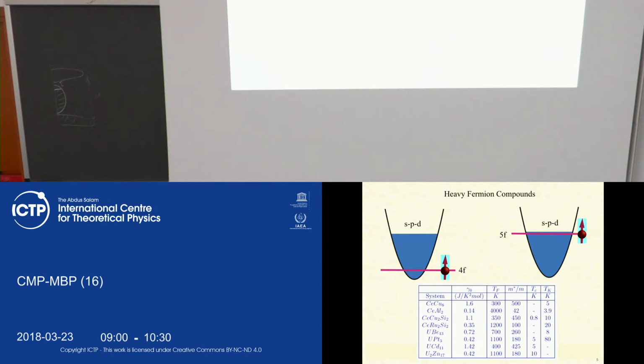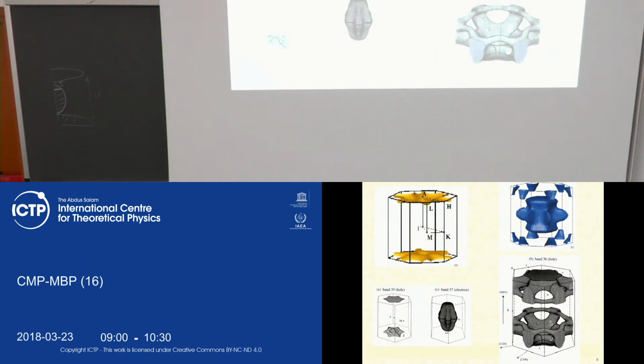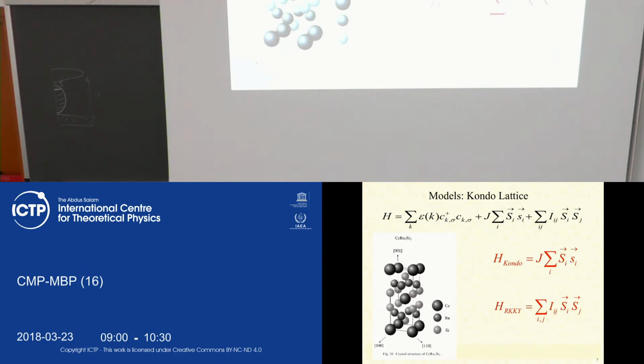One can also say that in this system you have spin 1/2 which interacts with conduction electrons. So in this sense, the system is in an integer valency regime. And here, since the 5f level is very close to the Fermi surface, there are very strong charge fluctuations, and this is probably the intermediate valency regime, because this f level can also contribute to the valency of your system. So this is how Fermi surfaces look like. In particular, this is the UPt3 system, if I remember well. And the question is, what are the models, how can one get this high effective mass?